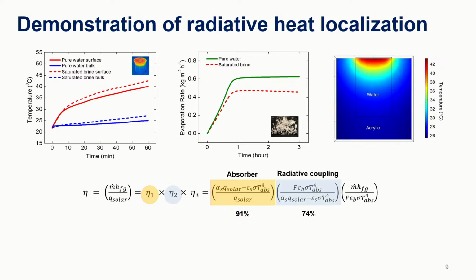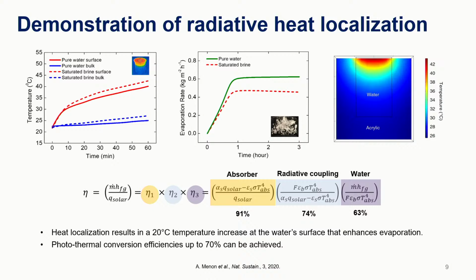Next, that heat has to be transferred from the infrared emitter to the water. And so in this case, because we're just using radiative heat transfer, we need very high view factors. And so you see there's some losses there in the system. And then finally, the heat that reaches the water surface, what percentage of that is used for evaporation versus other thermal losses. And so that's where you see we take a bigger hit. But overall, we can get to conversion efficiencies from sunlight to evaporated water of about 70% compared to what I showed you initially for these evaporation ponds where it's only around 20%. And so you can still do a very passive process, but by using the right materials and leveraging the inherent absorption properties of water, we can significantly increase that thermal efficiency.